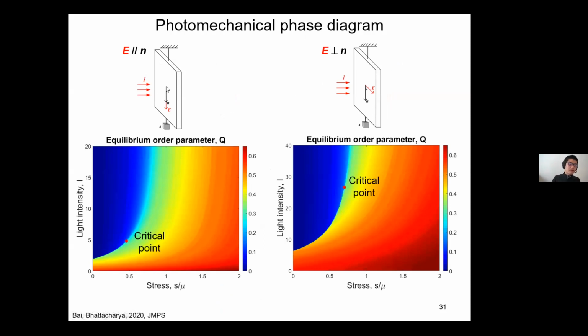This dependence on light polarization can also be seen in this phase diagram. I'm going to skip that quickly. Basically, we plot a phase diagram of this order parameter, and you can clearly see a critical point and a discontinuity here, which means it's a first order phase transition below the critical point. And if it's perpendicular, the coupling is weaker, so the critical point is higher, okay? Now we start to think, since you have a first order phase transition, it is possible that you can have some mechanical instability accompanied with this first order phase transition.